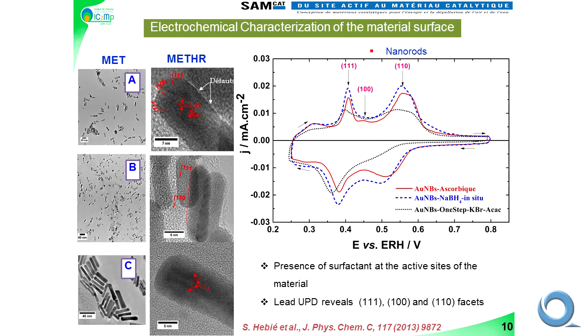We prepare directly here, for example, in this catalyst, we have a surfactant, and we prepare the seed-mediated growth, and after we add, for example, ascorbic acid as a reducing agent. At the same time, we change the reducing agent to sodium borohydride. The kinetics of the growth of the catalyst is very high. So we prepare this, and we have smaller particles with NaBH4.